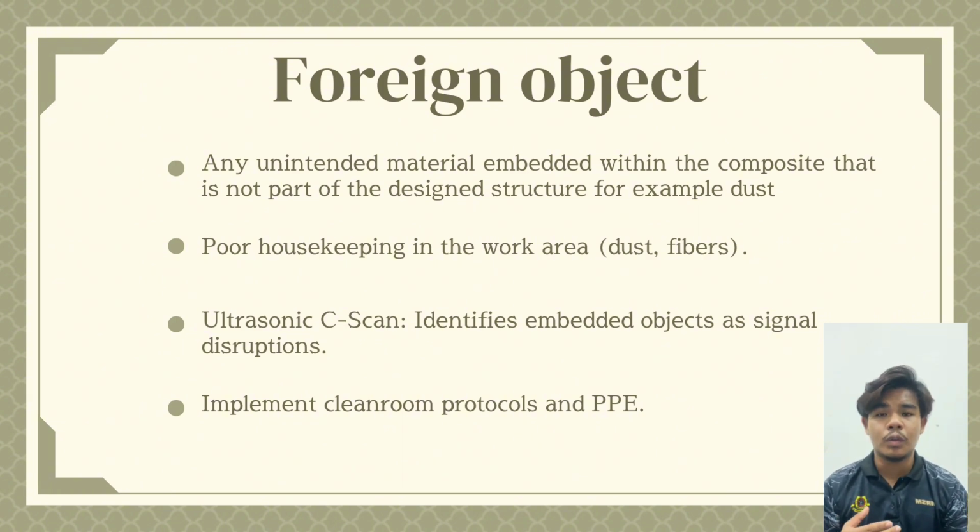So how do we detect it? A void uses UT, but to detect a foreign object we use the ultrasonic C-scan, to identify embedded objects that cause a signal disruption. A foreign object causes stress concentration in this area, which makes the composite less strong than usual.